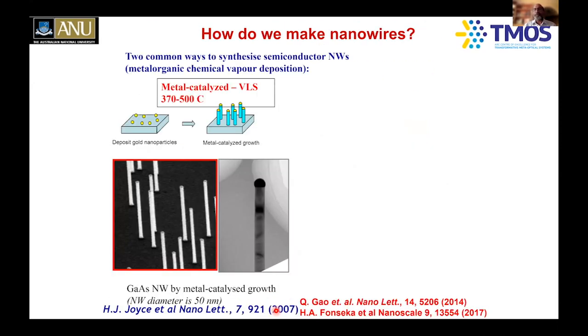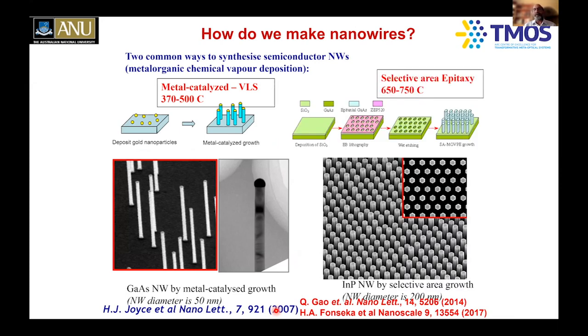So if the nanowires are so much of importance, how do you make these nanowires? There are two main techniques which we use. One is called a metal catalyzed VLS growth process, vapor liquid solid growth mechanism. And another is called selective area epitaxy. And we mainly use something called metal organic chemical vapor deposition, MOCVD.